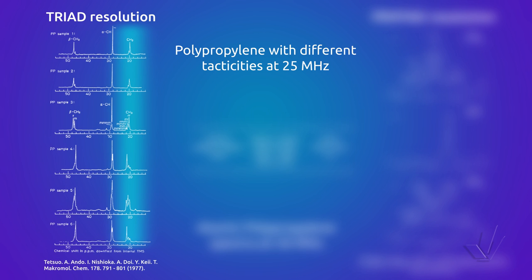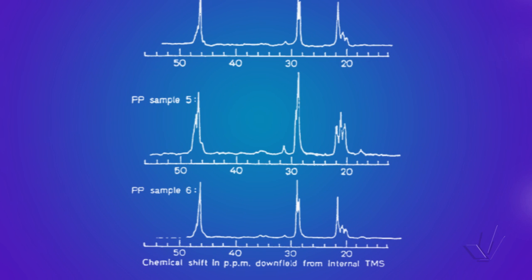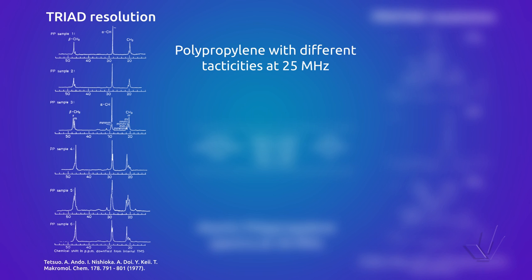That is why the methyl group is used to study polypropylene tacticity. In sample 5, the methyl is represented by three signals with an intensity of 1, 2, 1. This is a typical atactic polypropylene where all the stereosequences are in about the same amount. The first peak represents the MM triad, the second the sum of MR and RM triads, and the third the syndiotactic RR triad. In the other spectra, those three peaks vary in proportion depending on the percentage of isotactic, atactic, and syndiotactic triads.